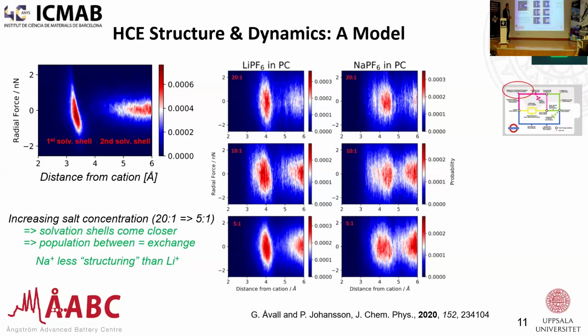But the really interesting thing is what happens when you're studying this as a function of cation or as a function of concentration. So you see when you're increasing the concentration now from 20 solvent molecules to 1 salt molecule, down to 5 to 1. So it's a very highly concentrated system. You see, especially for the sodium system here, that you have quite a lot of exchange. You have quite a lot of intensity between the solvent shells. And what does that mean? That means that you do have ligand exchange in a different way.